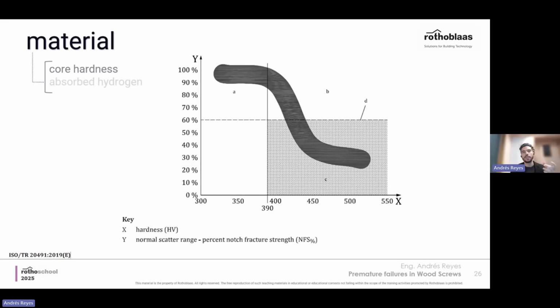So core hardness, of course, is how hard the screw is in its core. You generally measure it using a micro hardness. There are Vickers and Rockwell methods to measure the hardness at the center, at the nucleus of the screw. But what we see here is a relation between hardness, resistance, and hydrogen presence. So if you consider that this is a sample cloud, all of these are fasteners that were tested and gave these results, and they were summarized into a cloud.